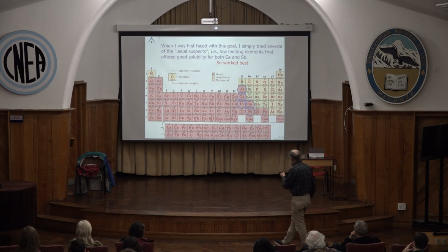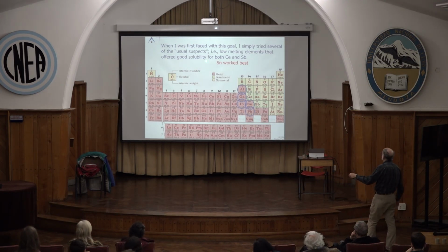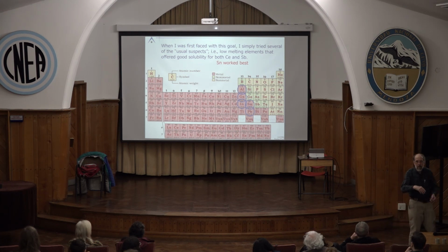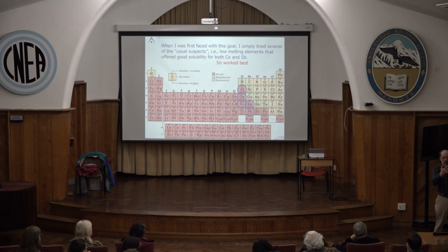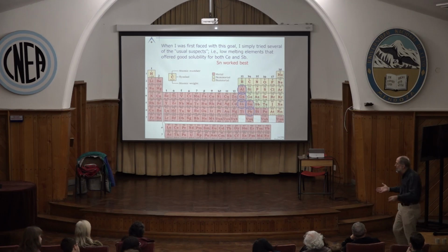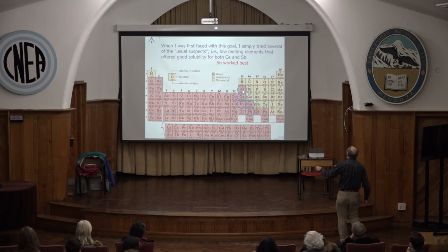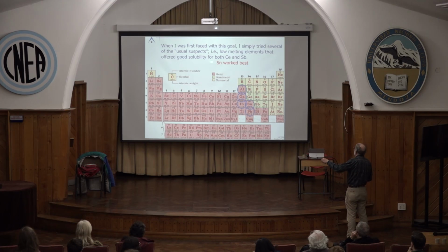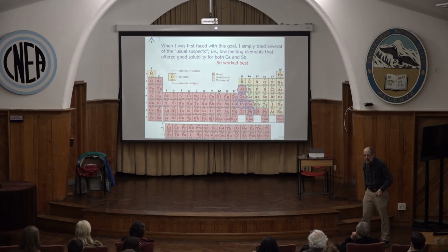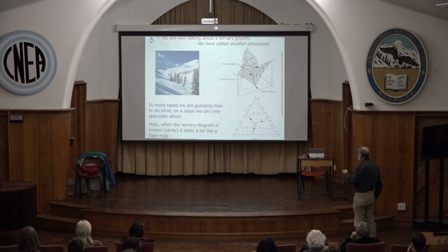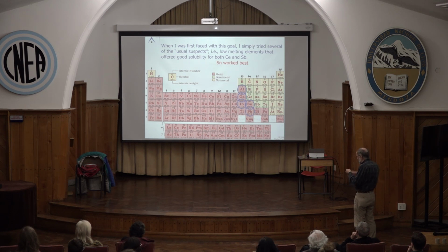So when I was faced with this problem 35 years ago, there were virtually no ternary phase diagrams, just due to the combinatorics. We have most binaries, but when you do 99 times 98 times 97, it becomes just a big number. There aren't that many of these. But what you could do is experiments. So I figured, let's look at the elements that are lowish melting, that can dissolve cerium and antimony, sort of the Casablanca approach of round up the usual suspects. And what I found is tin works.